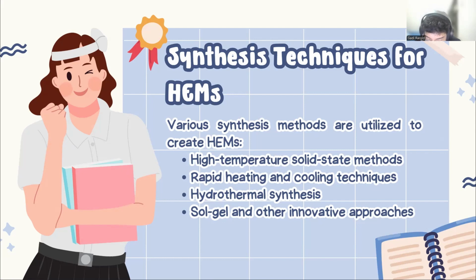For instance, Lu synthesized dual function catalysis, high entropy metal phosphide nanoparticles using the sol gel method, demonstrating exceptional performance in electrocatalytic reactions. While the thermal stability of high entropy catalysts produced via the sol gel method remains inferior to those synthesized through high temperature pyrolysis, these catalysts exhibit unique morphology and high specific surface area, leading to outstanding photocatalytic performance.